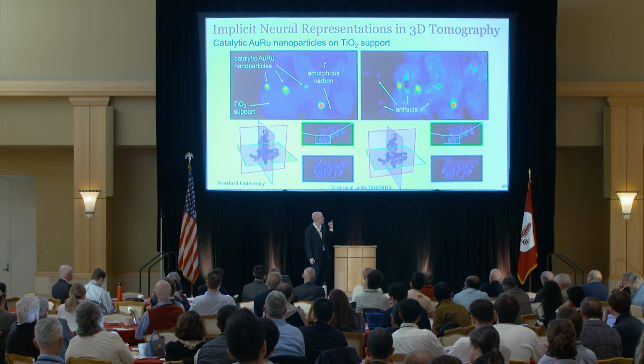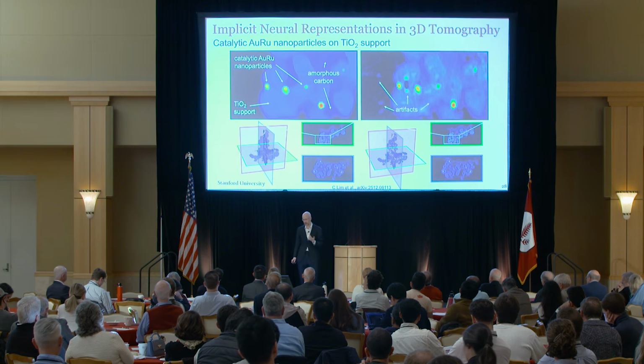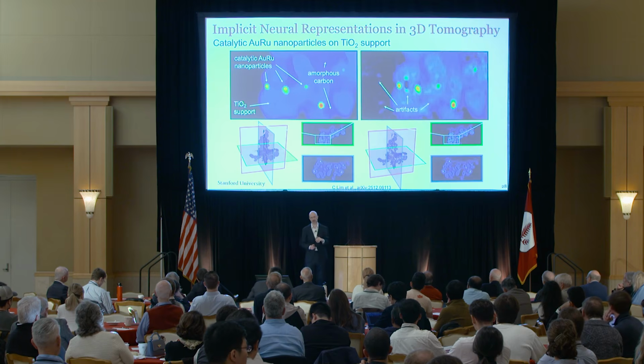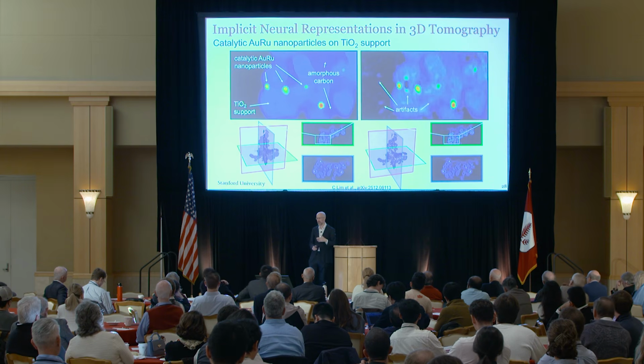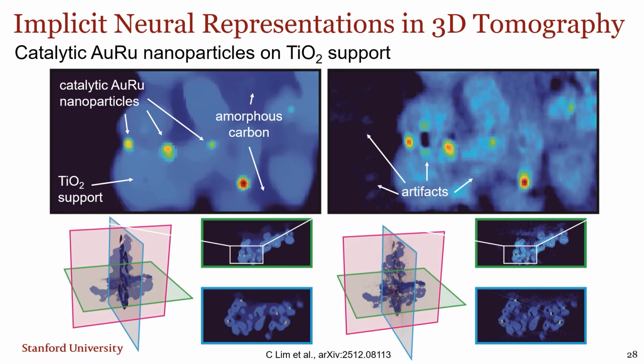And if you imagine the conventional reconstruction is all you have to go on here, you can see the nanoparticles, but the support constraint is essentially completely blurred out by these artifacts, by these extra errors, and that's just caused by missing information. We can't fully tilt the sample 360 degrees, and our measurements are not sampled at 0.1 degree increments. We have a limited number that we can perform here.